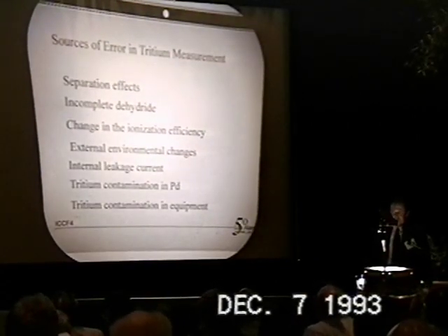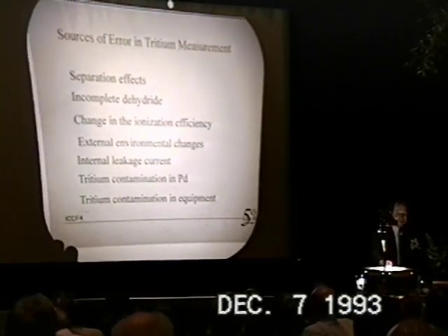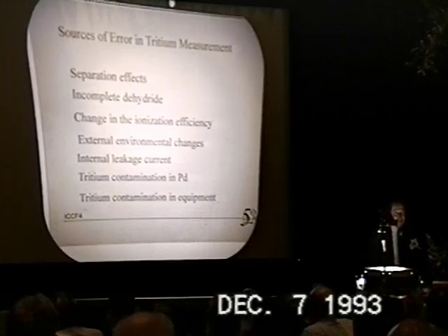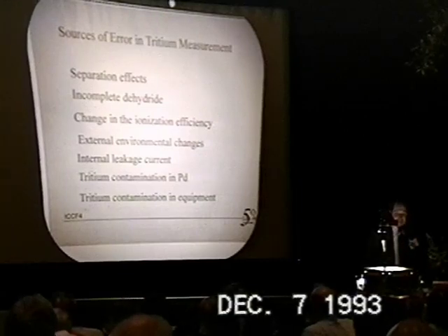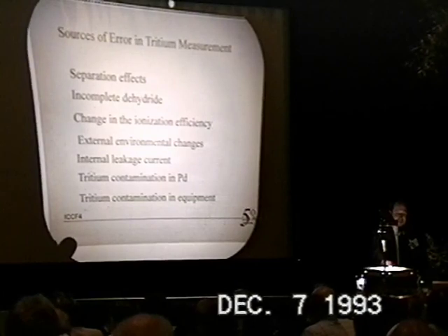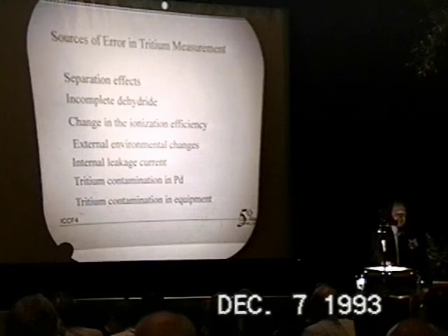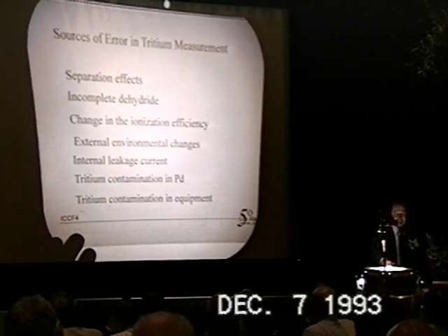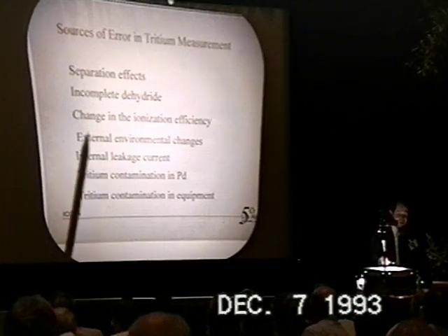If you're looking for tritium levels this low, there are obviously lots of sources of errors. We're doing our best, and perhaps later on I'll come back to some of these as we go through the results. First is separation effects. Coupled with that is the second one, incomplete dehydriding. If you don't dehydride completely, the last gas coming off will be rich in deuterium. We avoid that because we essentially pull off all the gas. We see the separation effect when you sum up all of the aliquots, or you completely dehydride the sample, that takes care of that.